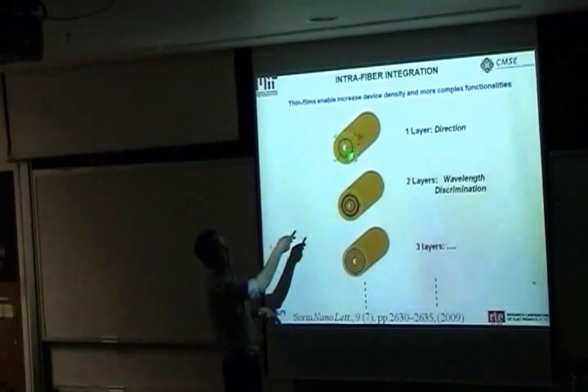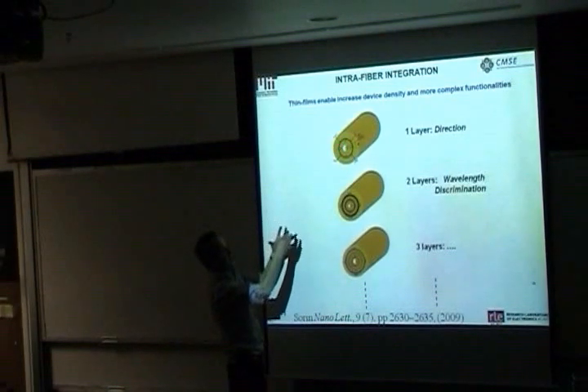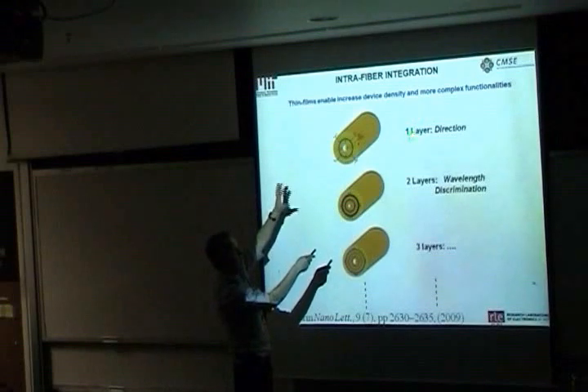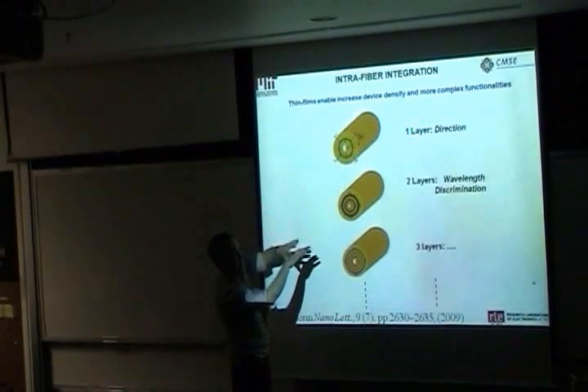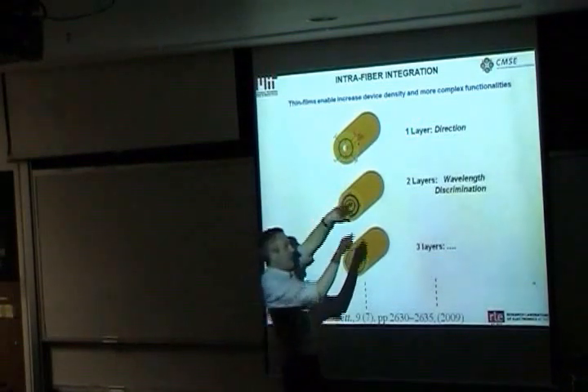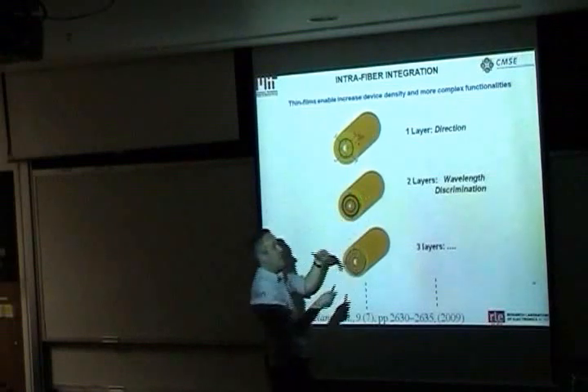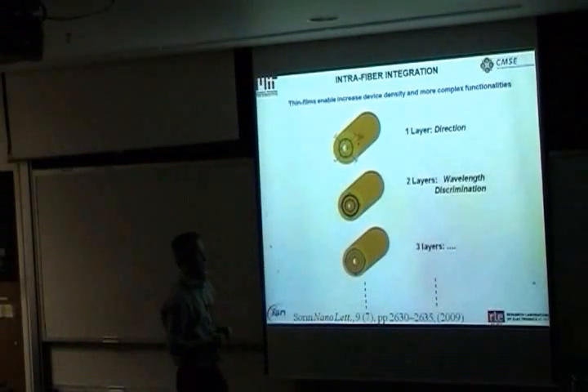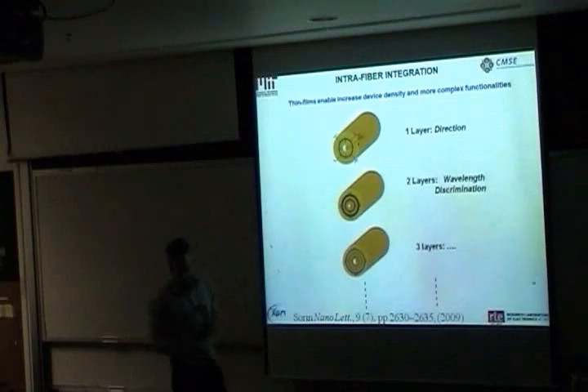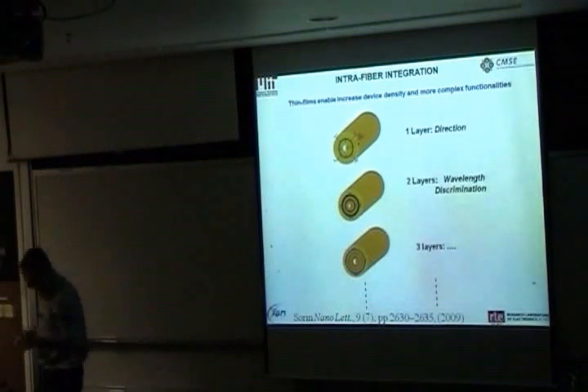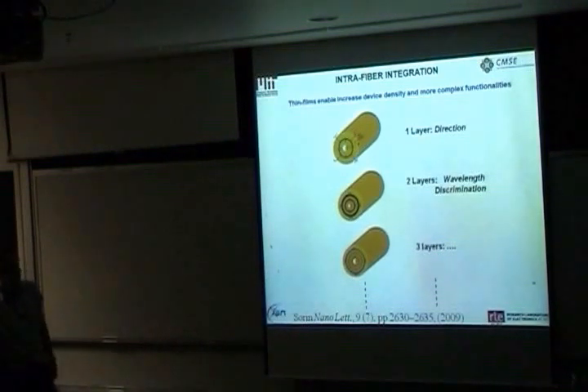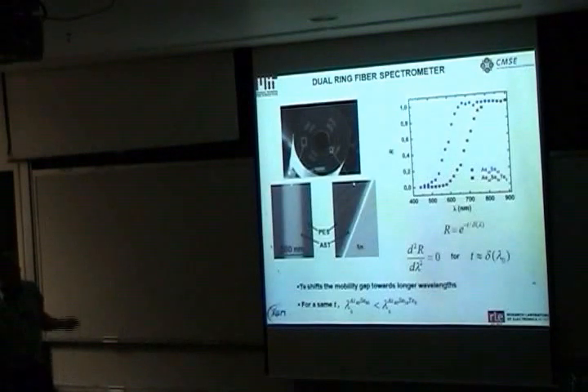And it turns out that if you put one layer of semiconductor with these four metal electrodes, you could get direction of illumination now on a single fiber. If you put two layers, the light that comes out back through these could actually be wavelength discriminated. And if you put three layers, you could actually map your intensity and your light into a color scheme. This is work that was published over the summer in Nano Letters.